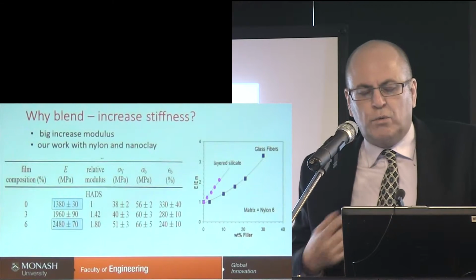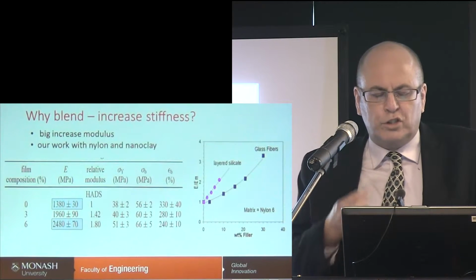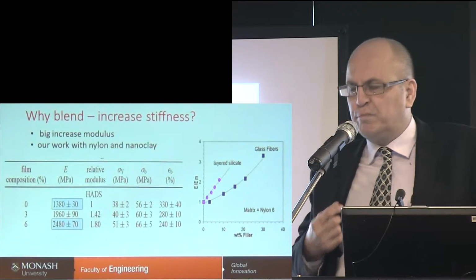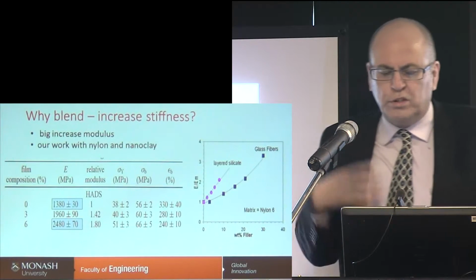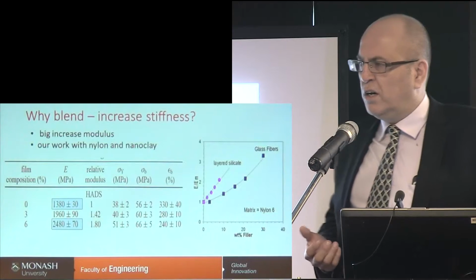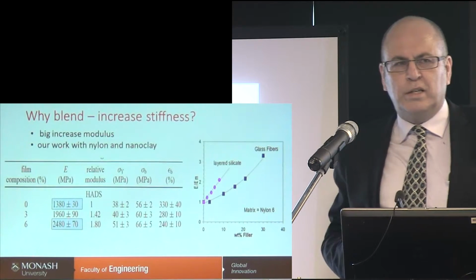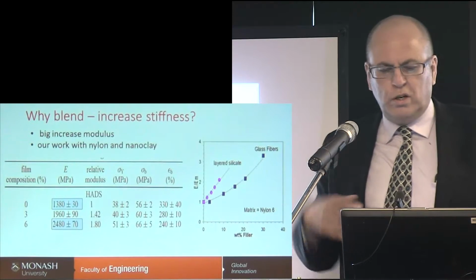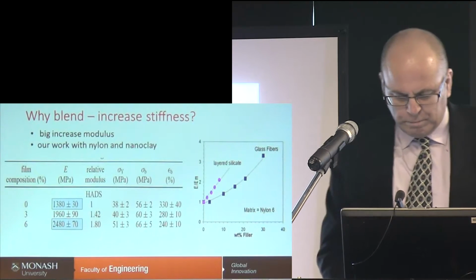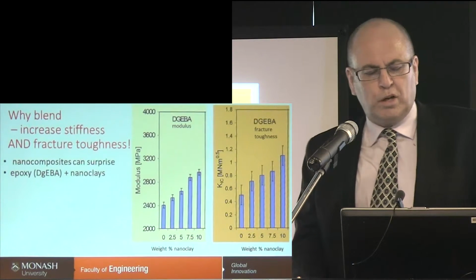And it's not our data on the right, but it's a classic diagram often shown where you can see that less than 5% of filler can double the modulus of something, whereas if you use glass fibres in that nylon, you need about 20%. That's much more viscous, it damages your processing equipment and so forth. Causes degradation of the polymer.